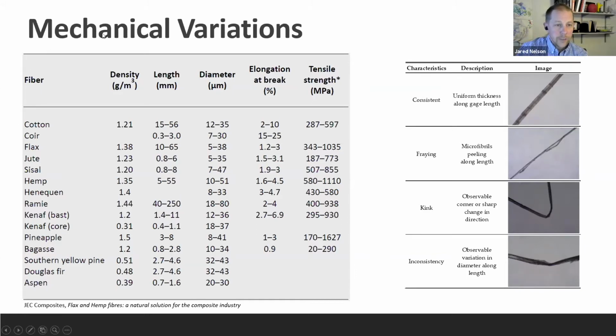Notice the variation. Density is pretty consistent, right? Density is listed as a single number. However, fiber length is a range. Hemp goes all the way from 5 millimeters to 55 millimeters. That's a factor of 11, a huge variation. Similarly, our diameter ranges from 10 microns to 51 microns, a factor of 5, again a huge variation. We see our elongation at break varies by a factor of 3, and our tensile strength by a factor of 2.